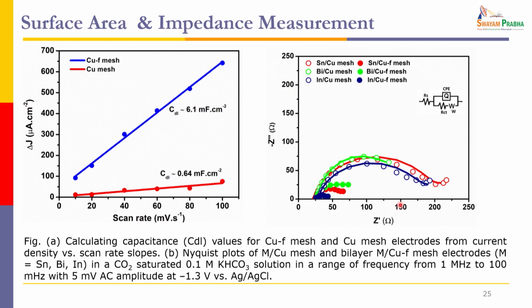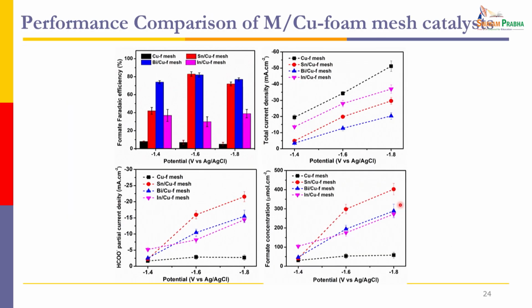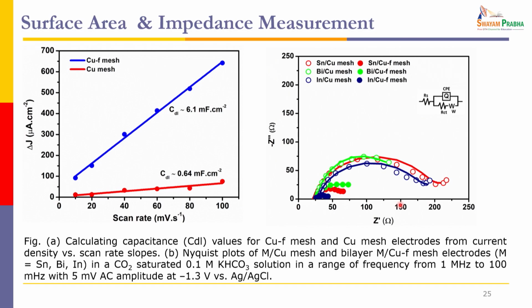Earlier, if I go back, there is a change in activity between the regular one and the deposited one. The base substrate itself, since it becomes a foam, has a high surface area. That is one reason, and conductivity also changes. This is an impedance plot where the smaller the value, the better the conductivity, because when you have a large circle, your resistance is high. So you need to see low resistance. The copper foam which was made has a low resistance and is better in terms of conductivity compared to the one without foam. So we have made a material with high surface area and low resistance. That is the base, and one of the reasons why the formate Faradaic efficiency is higher.